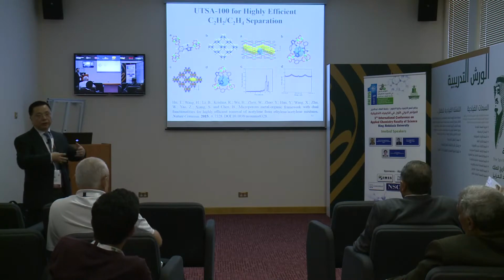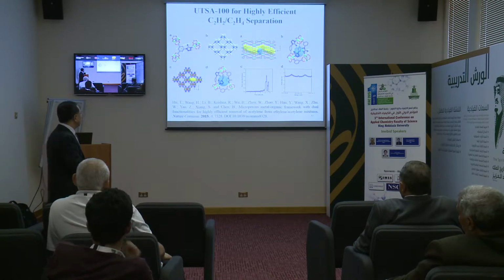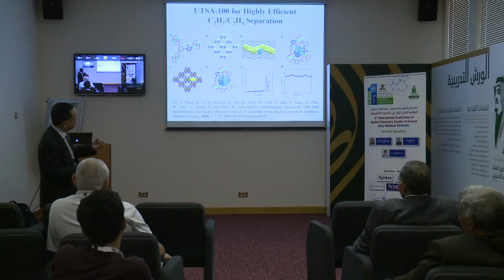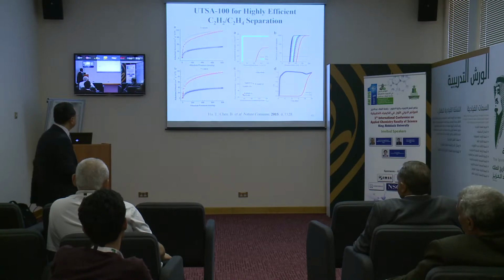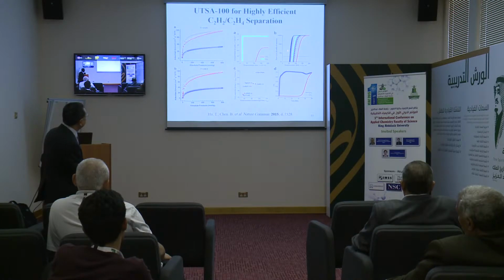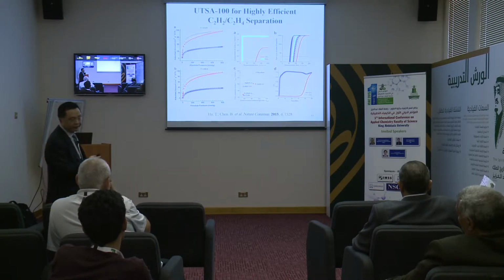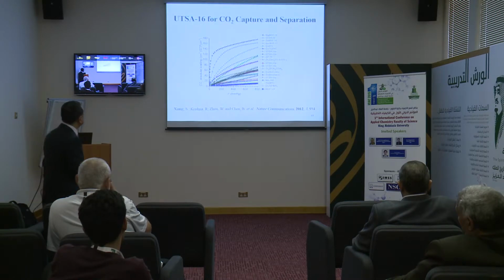So overall, these materials have moderately high porosity and also uptake. So the separation here is much higher than other types of material, and further confirmed by experimental breakthrough. So this is related to productivity. So this is a unique example.